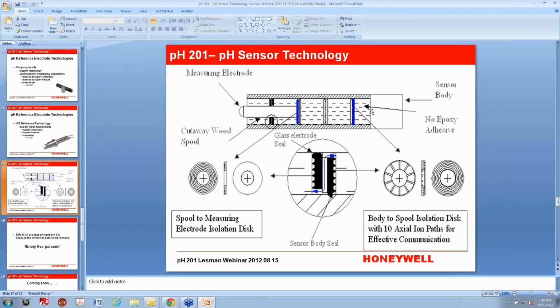And the reference electrode, and I forgot to put it in this drawing, my apologies, but right here at the back would be the reference electrode. It's 50 times the size of a standard silver chloride reference electrode. It's all the way at the back, and it's well protected. So if you were to take this sensor and put it next to any of those other technologies in a plain water application, it will probably have the same lifespan, because the lifespan in that application is going to be based on the active sites on the glass, how soon they wear out and get coated up, etc. But the nastier the process gets, the better this technology looks.